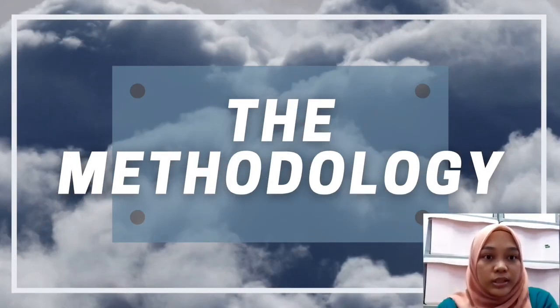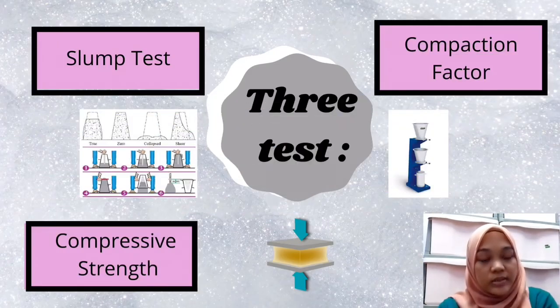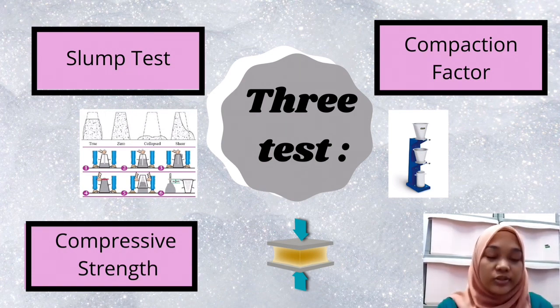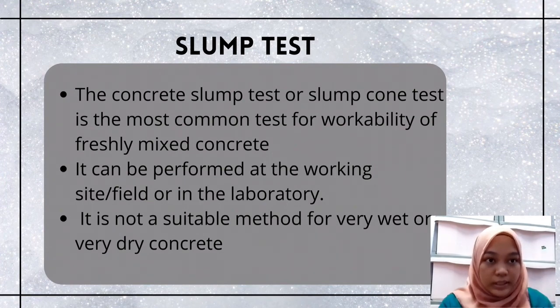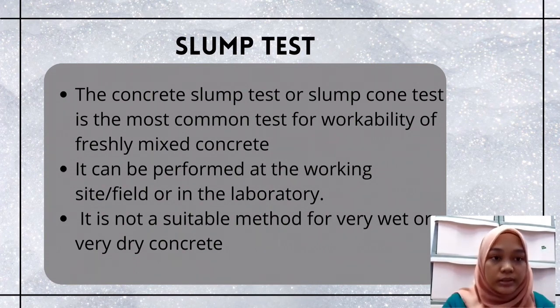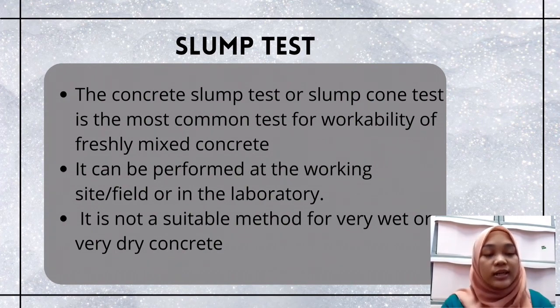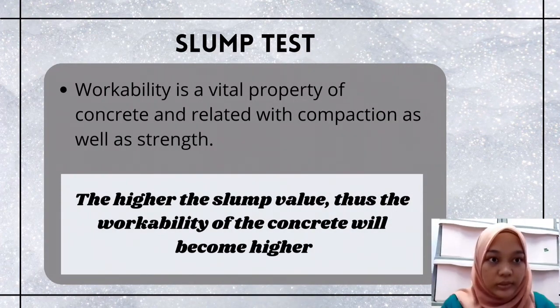Next, the methodology used by these researchers consists of three tests, which are the Slump Test, Compacting Factor, and Compressive Strength. The Slump Test is the most common test for determining the workability of fresh concrete. It can be performed in the laboratory or at the construction site directly. However, it is not suitable for very dry or very wet concrete. The result obtained from this test is a slump value, which indicates the workability of the fresh concrete.